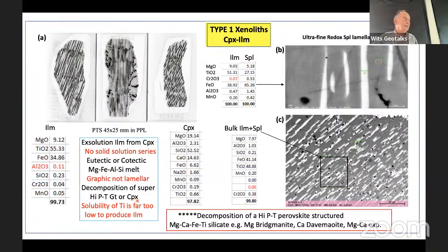But the problem is, people who've worked in ultra high pressure areas have found similar intergrowths, except they're olivine. Olivine plus ilmenite, olivine plus titanium magnetite, olivine plus rutile. And what they point out, correctly so, is that the solubility of titanium is far too low in garnet or clinopyroxene to produce the ilmenite. So it cannot, as Ted Ringwood and Barry Dawson suggested, perhaps these were super high pressure temperature garnet and clinopyroxene, that's not possible either.